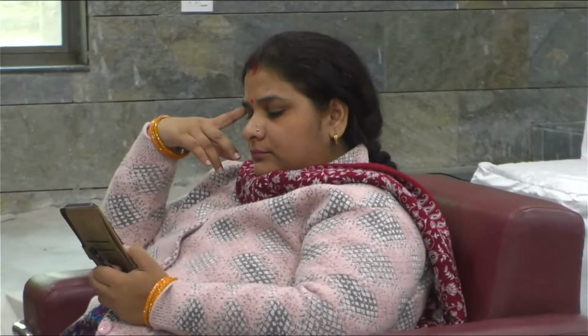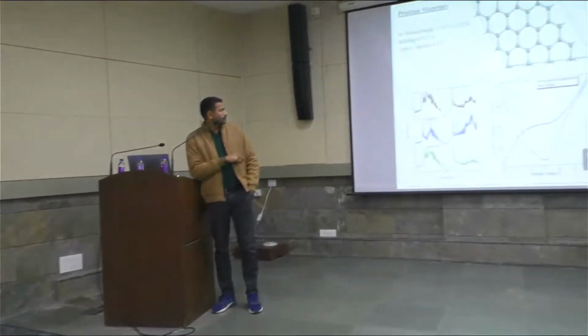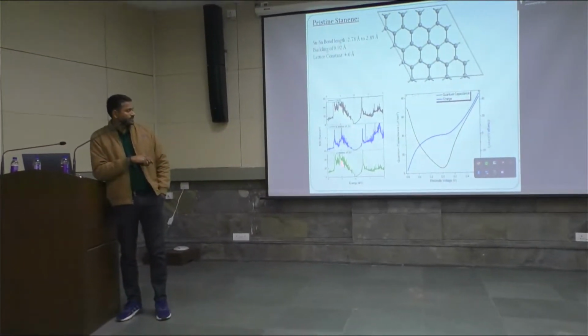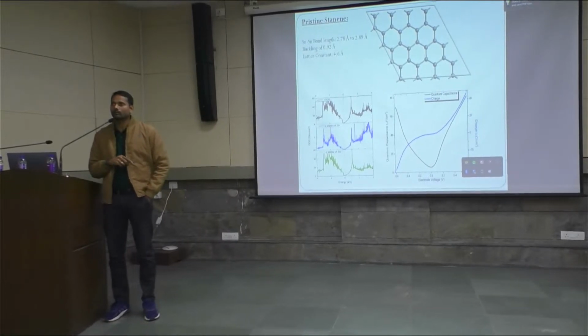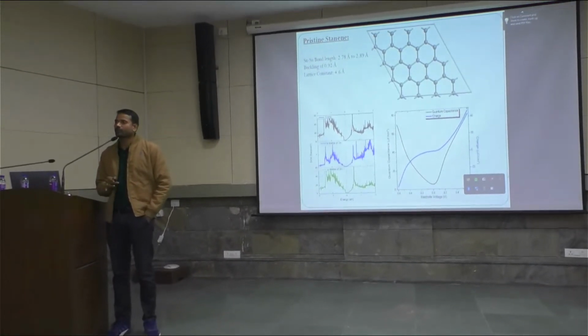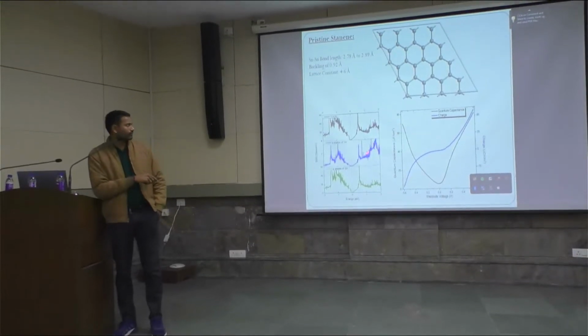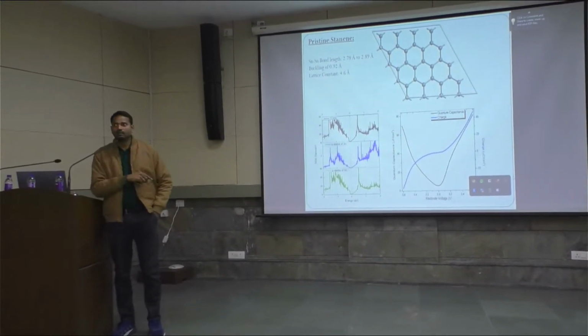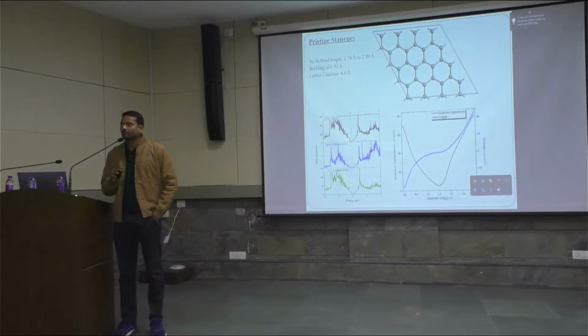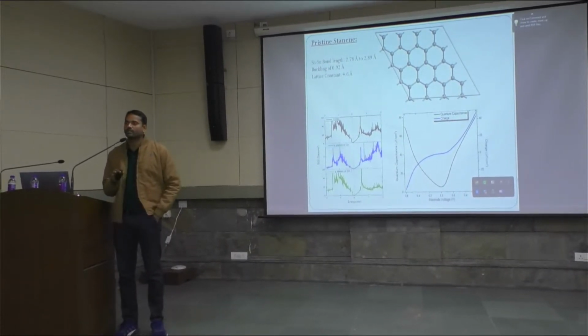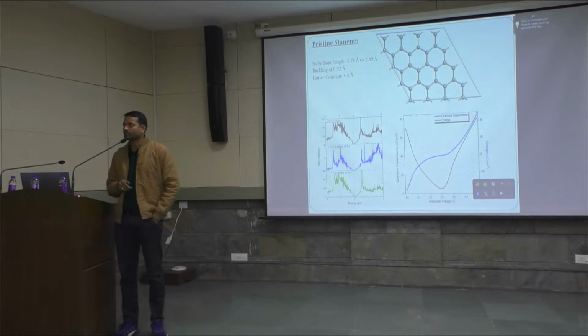I have taken stanene. First, I analyzed the pristine stanene. In pristine stanene, first we extracted the density of states, and we confirmed that stanene also offers zero band gap, just like graphene. But the PDOS shows there are s states and p states. In pristine graphene we see only p states because of the sp2 hybridization. But in stanene, we have both p states and s states, and the presence of s states indicates there is sp3 hybridization also, and the report says stanene has sp2-sp3 coexistent hybridization.